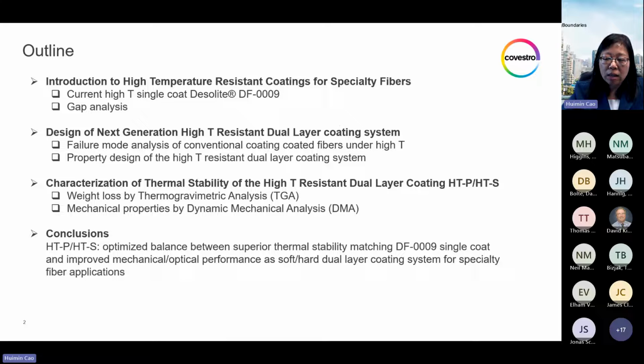To explain the design of our new dual layer system, I will show a failure mode analysis of how conventional standard coating would fail under this high temperature aging, and how we designed our new coating system to avoid these failure modes. The high temperature stability is characterized in the lab with film samples by a commonly used weight loss measurement by TGA and the mechanical properties by DMA.